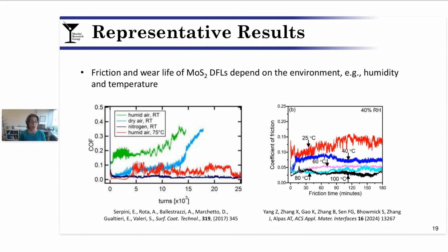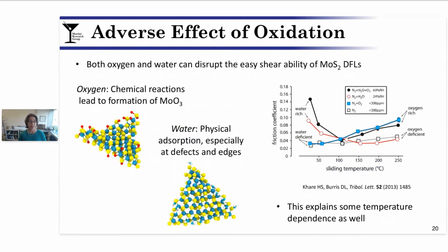In the figure on the right, the tests were performed all at 40% humidity, but at different temperatures above room temperature. And this result shows you that friction decreases with increasing temperature, again, above room temperature. So there's clearly a sensitivity to the environment of the MoS2 dry film lubricants. This can be largely attributed to the interactions between the MoS2 and oxygen and/or water, both of which can disrupt the easy shearability in different ways. Oxygen can chemically bond with the molybdenum disulfide to ultimately form MoO3, a less lubricious counterpart.